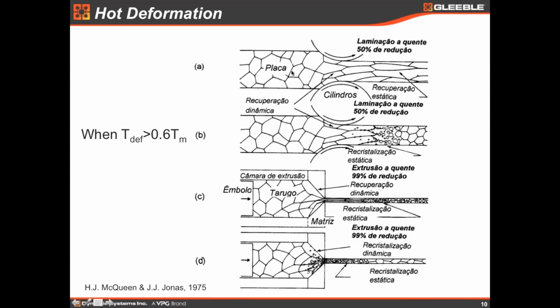In the upper case, in rolling, we have a high stacking fault energy metal, let's say aluminum, where the recovery happens very fast. So we see that in the deformation zone we create some dislocations and we don't have any new grains generated. There is no recrystallization because the rate of recovery is very fast and it decreases the driving force for recrystallization.